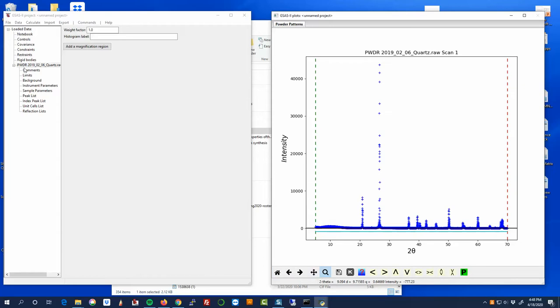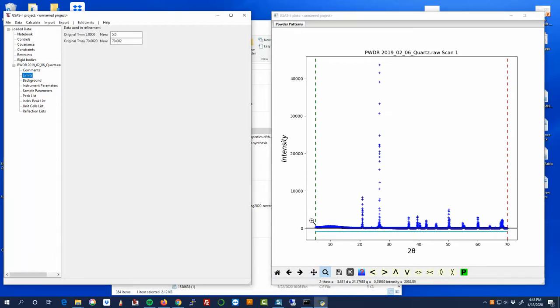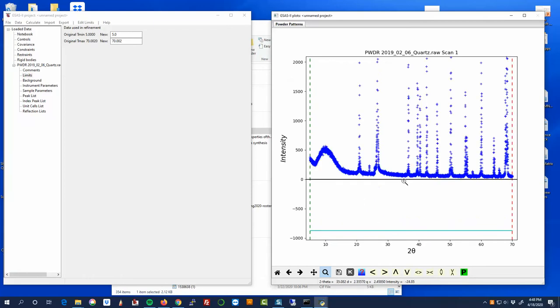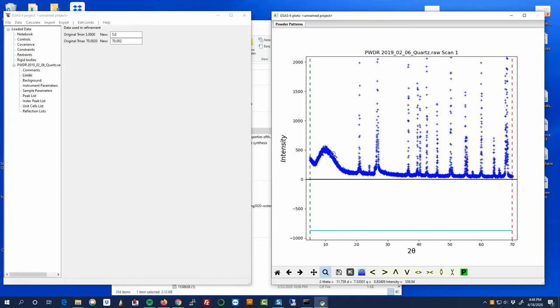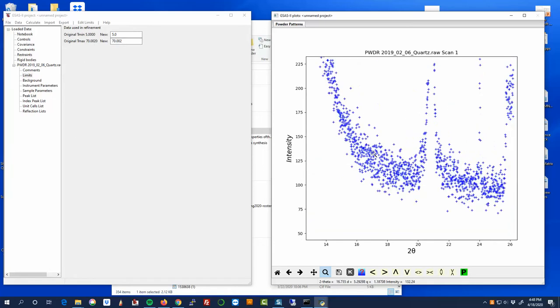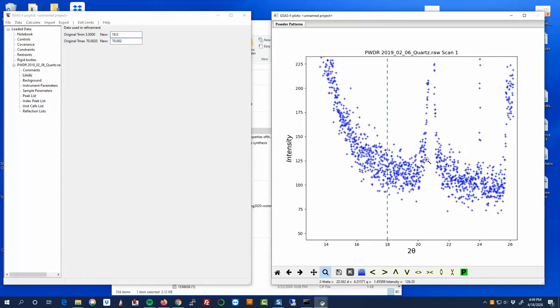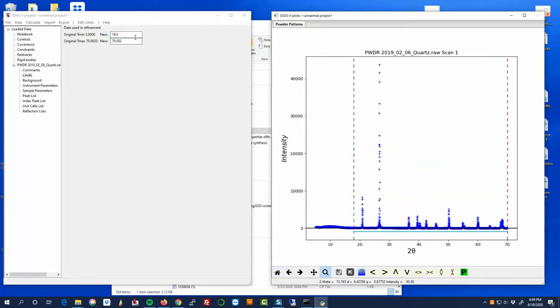And the first thing that we're going to do is we're going to set some limits on that data. And the reason we're going to do that is if I zoom way in here, all of these sharp things are peaks that we're interested in. This broad hump at the beginning is a signal from an amorphous background. So this either means that we have some amorphous SiO2 mixed in our sample, or more likely we actually were shining a little bit of X-rays on a plastic sample holder. And that's what's responsible for that peak. But that's not data that we care about. We're not going to worry about that in this refinement. And so I'm going to say, you know, pick an angle somewhere down here. Let's say maybe 16 degrees 2-theta, or you could use 18, something like that. That is before the first peak. And we're going to use that as our new cutoff. And so once I do that, now all of the refinement is really only going to apply between 18 and 70 degrees 2-theta.